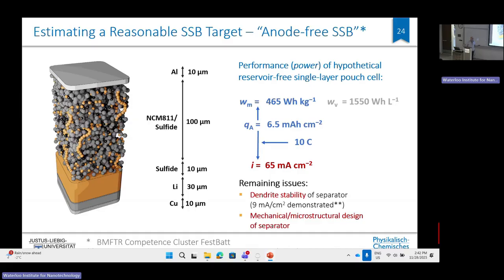Of course, OEMs would like to see that also for cars, but it's not yet achieved due to all the instabilities in cells. But 10C would mean for this cell 65 milliamps per square centimeter current density, which nobody has ever really tested. I think for lithium metal, Peter Bruce demonstrated 9 milliamps per square centimeter critical current density without cracking.